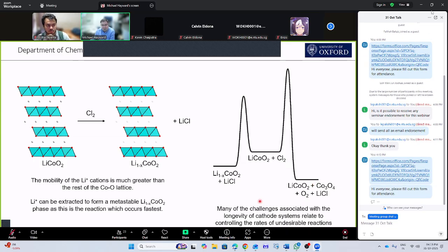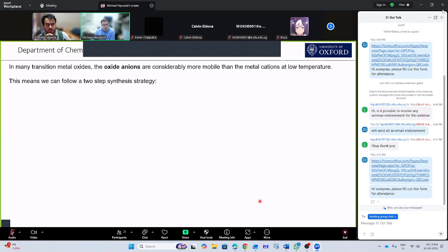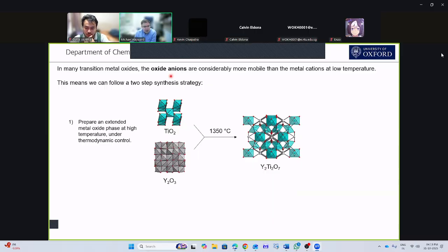Okay, so what we find actually in many transition metal oxides is that the oxide ions are the most mobile species, much more mobile than the metals. And so what we can do is follow a two-step synthesis strategy. Step number one, we can do a conventional thermodynamic high temperature synthesis.